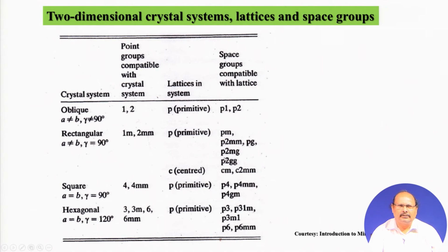And finally, you can also have simple rectangular two dimensional lattice. You also have a situation where you have a two-fold axis symmetry that is vertical, and you have two glide planes at orthogonal relationship here, and we call this the symbol P 2 G G. In case of centered rectangular plane lattice, C combines with simple M and C combines with this 2 mm here.